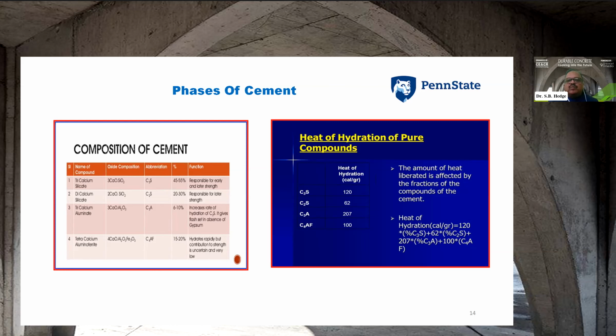Another slide which I placed is the heat of hydration of these compounds. From this slide you can see that the maximum amount of heat is emanated by C3A, followed by C3S. So the heat of hydration can be reduced if you control the C3S percentage and C3A percentage by adding cementitious material. So just keep this in mind.